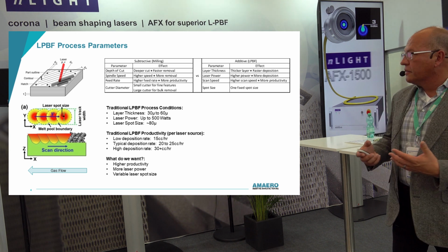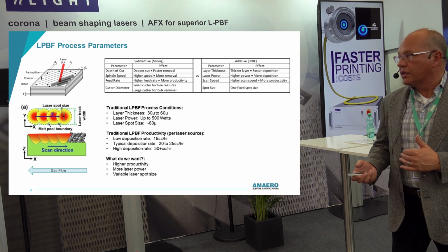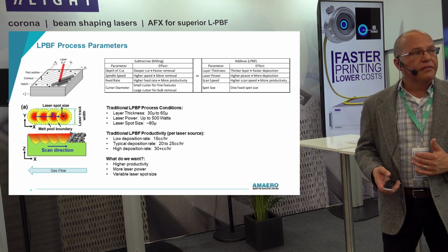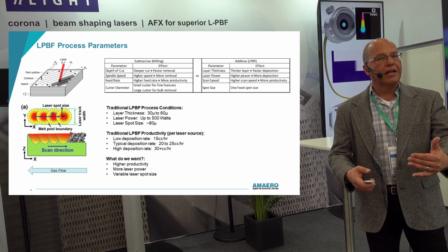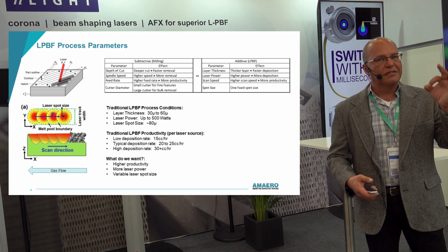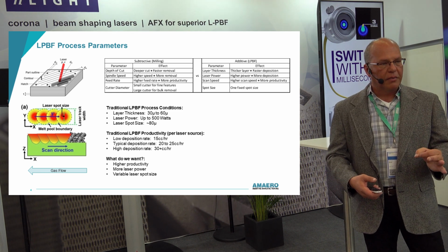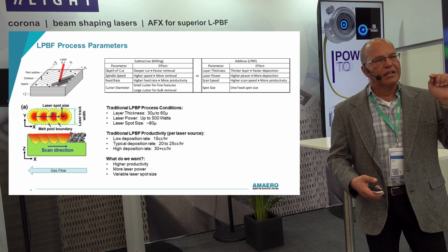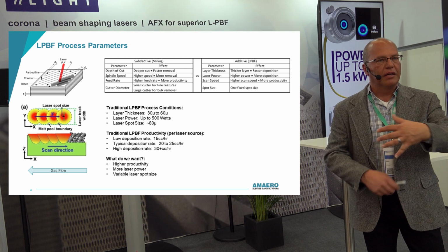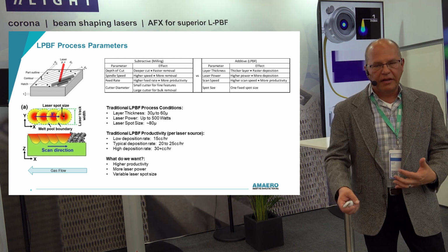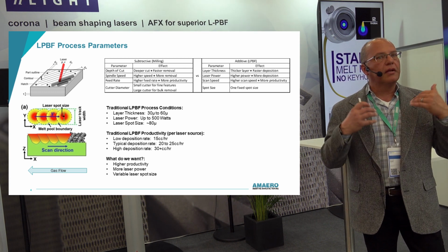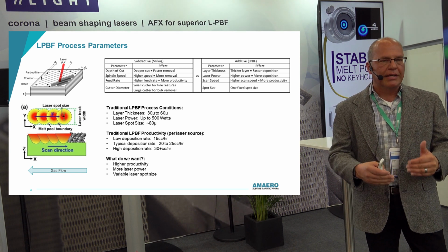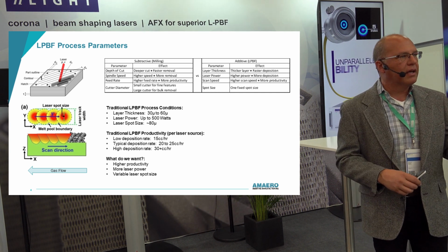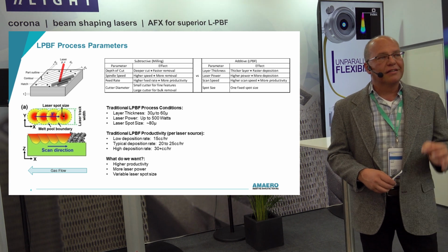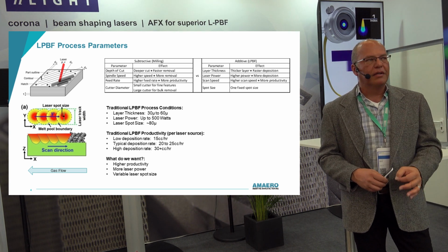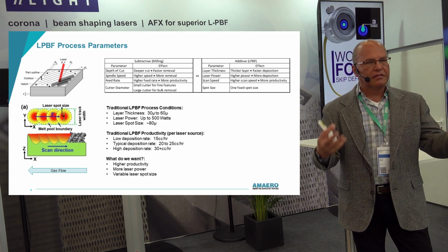Traditionally, our printing is in layer thicknesses from about 30 to 60 microns, up to about 500 watts. We have more powerful lasers, but with an 80 micron Gaussian spot, if I go over 500 watts, I'm just going to keyhole, drill deep into the metal, and create lots of porosity, lots of defects. And if we're sending a lot of power in, we're generating condensate. We're not selectively laser melting. We are selectively laser boiling. We are boiling the metal, generating lots of vapor.